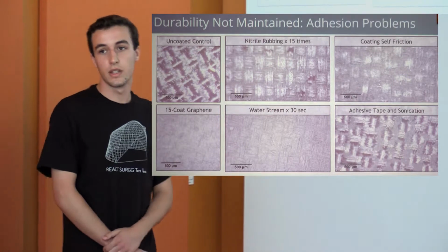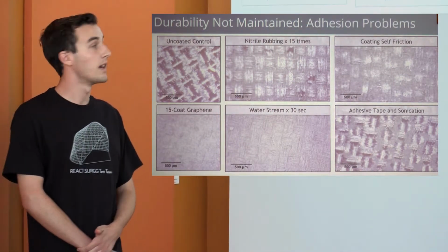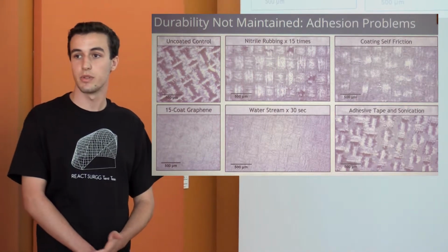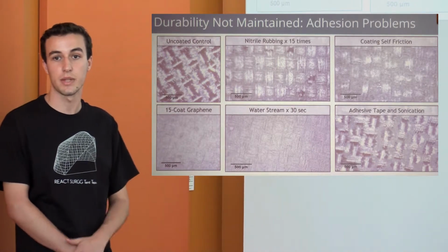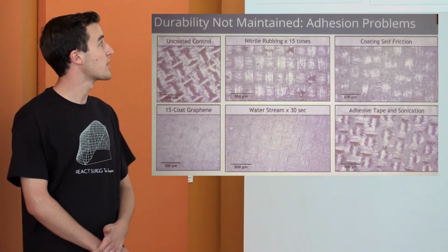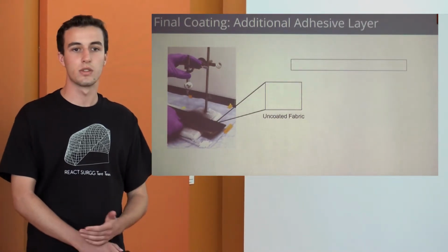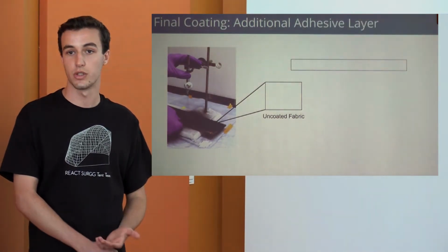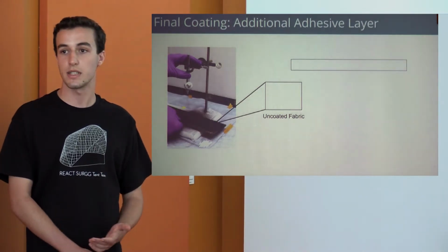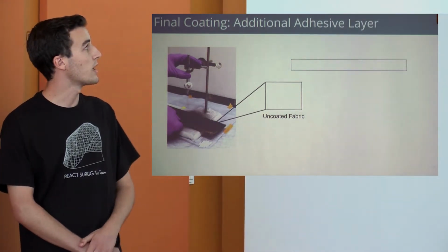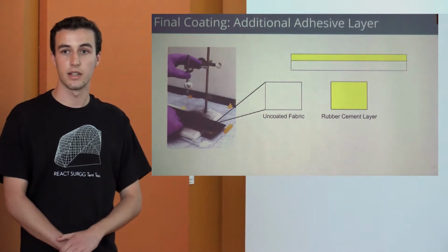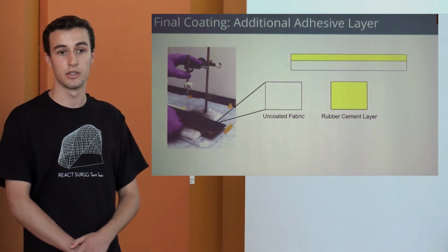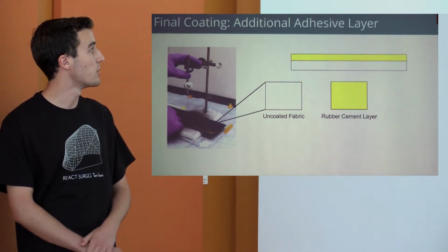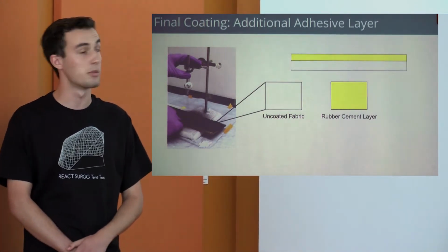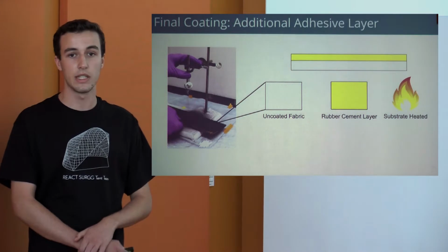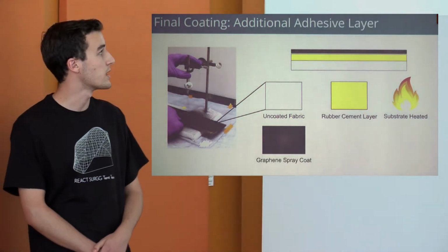Okay, so when the characterization team got back to us and said that the coating had the superhydrophobic properties, but it was not that durable and it lost these after some basic durability tests, we went back to the drawing board and started thinking about what sort of adhesive layers we could add to make the coating more durable. So we started trying out different sorts of epoxies and adhesives. We found out that using a commercially available rubber cement as a base layer greatly improved the durability. So for the final coating, we wound up doing the uncoated fabric, then a layer of the rubber cement. Then it was briefly heated with a heat gun before applying the graphene spray coat.